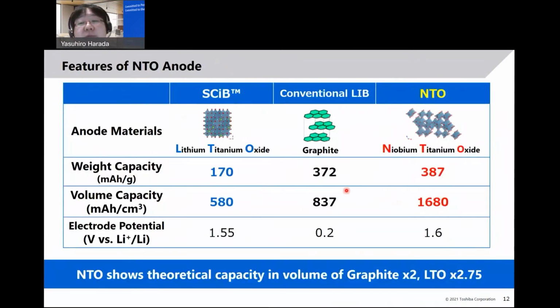This table shows the features of NTO anode material. Compared with currently used LTO and conventional graphite, as I mentioned, we are now focusing on the development of niobium titanium oxide. This material has much higher energy density compared to LTO. Especially the weight density, energy density is comparable to the graphite. Moreover, the volume energy density is twice as much as graphite. That's why we are keen to develop this niobium-based material.